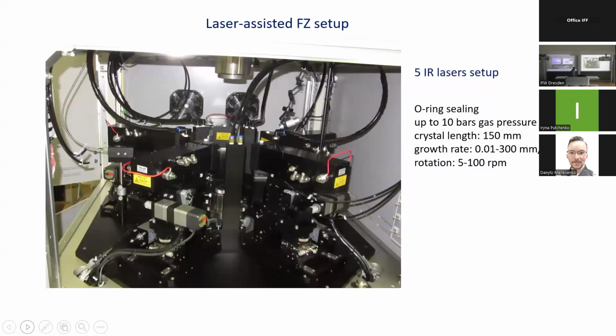Okay, now a few words about this laser-assisted floating zone setup. So it's the main part of the furnace. You see five infrared laser diodes. Here you see one of the laser beam stoppers. It's just a water-cooled metallic plate. Technical specifications are very similar to the conventional image furnace. We use O-ring sealing, so the gas pressure up to 10 bars, crystal length, growth rate, rotation.